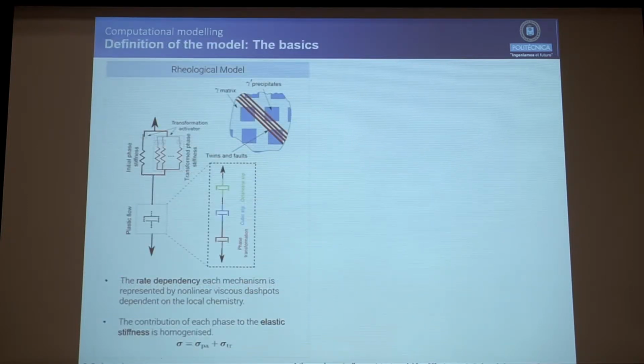So this is a summary of the rheological model. Basically, we take into account the elasticity of all the different phases. At the beginning we will just have the parent phase, but as the material is deforming, we will start to create the twinning phases if the conditions are favorable, and the stress is a combination of all these phases together. In terms of plasticity, we take into account the three main deformation mechanisms in superalloys. So octahedral slip, which is just full dislocations shearing the gamma and gamma prime precipitates. Then cubic slip, which is a mathematical artifact for continuum modelers to take into account the dislocations jumping the gamma prime precipitates, the cubes. And finally, we have the phase transformation, which is basically the microtwinning mechanism.